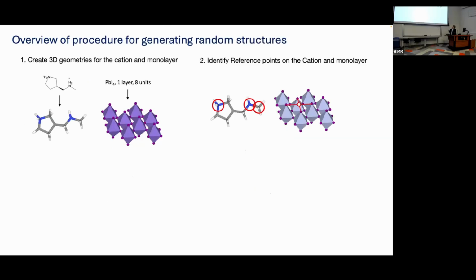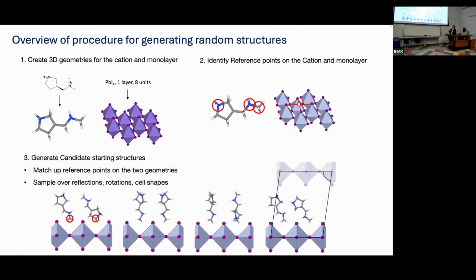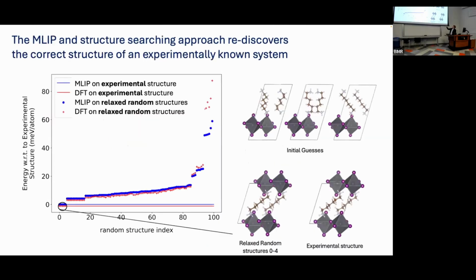So in this case, we encoded several different heuristics that we observed from the database, basically where the organic is placed, because they have these amine groups. That makes our problem a little bit simpler. But ultimately, we get pictures like this, where we have these different permutations and their placement on the surface itself. Because we have many different guesses, we have all of these energies that we have to